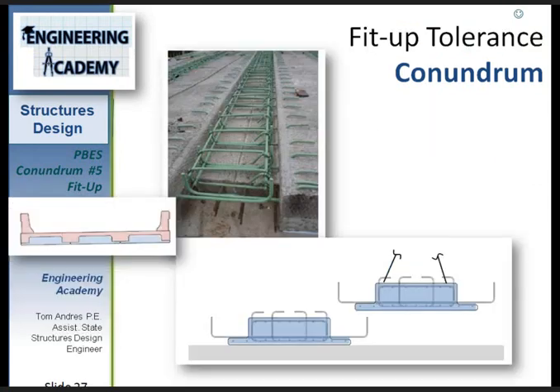Another common fit-up issue found in PBES applications has to do with rebar conflicts. Here you can see a very successful pre-stressed unit section developed in Minnesota, which eliminates the cracking in the concrete topping at the joints. This is really a nice section and a good solution. However, as the slide shows, the rebar detailing makes unit placement difficult because of potential conflicts with the tails of the rebar overlap. So the units must be placed far enough apart so that the rebar does not conflict, and then they're kind of slid sideways horizontally into place, right?